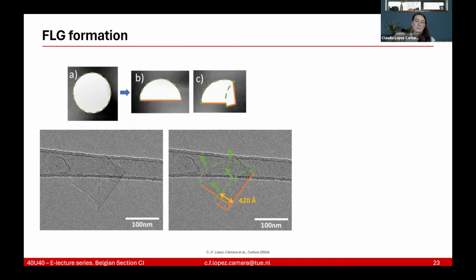So the top part, A, B, and C, is just a piece of sheet that I cut in a circle and made in half, and then I did another folding in order to mimic the picture that I saw in the TEM, which is the picture that you see below. Both of the pictures below are the same picture. The one on the left is the raw picture from the TEM. The one on the right is the picture that I tried to help people see what it actually looks like. The green part would be mimicking the picture in C, which still allows growth because there is no bend or curvature there. However, the orange part is the part where you cannot have more growth of graphene. And that also explains perhaps why we get such a crumbled graphene.